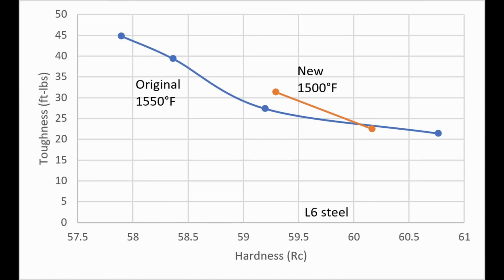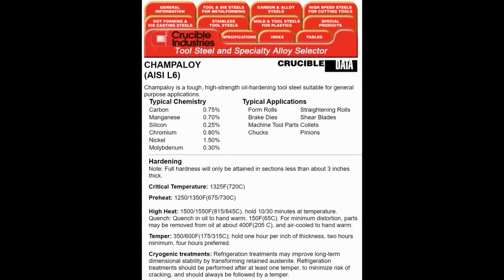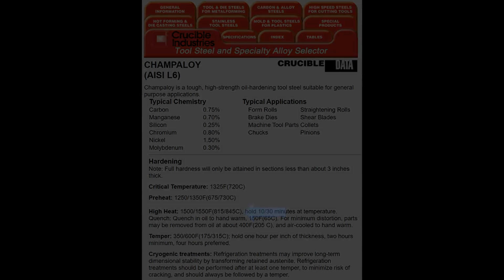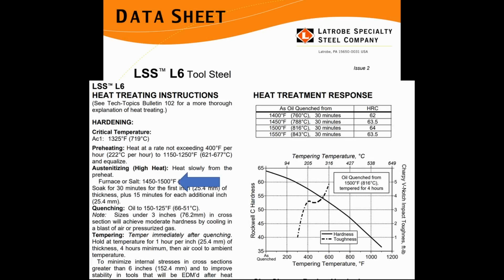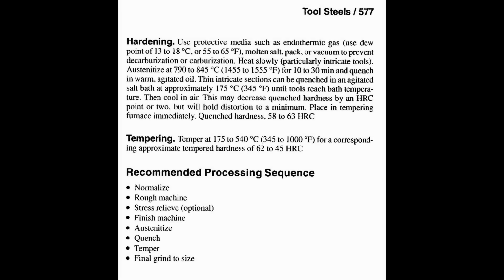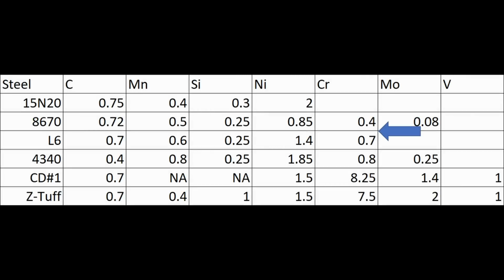So I also did a new study on this steel because one of the criticisms of Warren's original heat treatment is that he used an austenitizing temperature of 1550. And the Crucible datasheet says use 1500 to 1550. The Latrobe datasheet says use 1450 to 1500. The ASM Heat Treaters Guide says use 1450 to 1550. And I know that 1500 works very well for 8670, which is also a chromium-containing nickel alloyed steel. So I thought, okay, I will redo this experiment but use 1500.